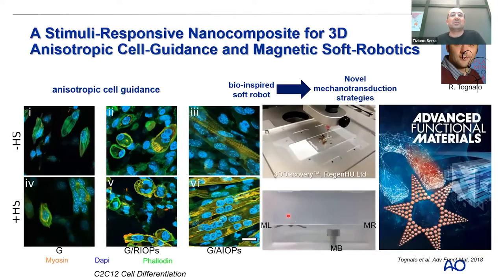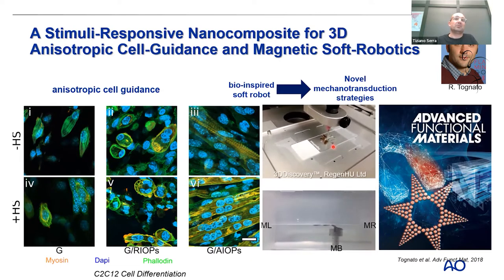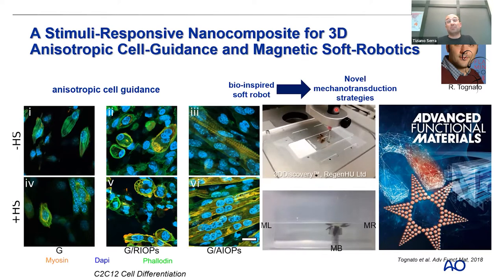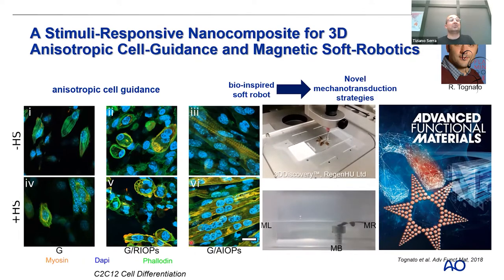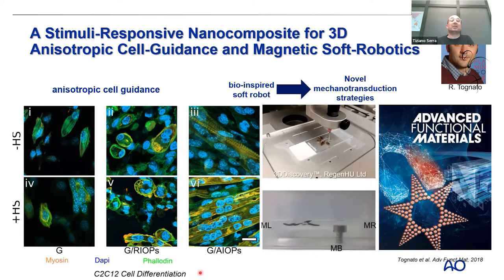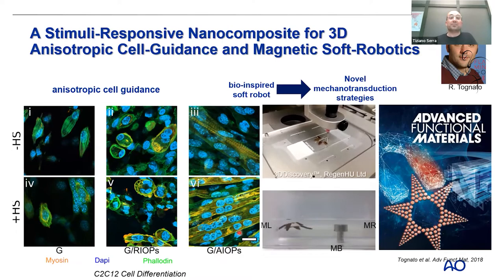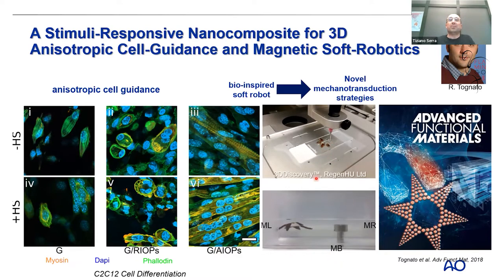We have recently studied the bioprinting of an ink that is a nanocomposite containing inorganic particles — in this case iron oxide particles — which give the bio-ink magnetic properties. We can use anisotropically aligned particles through a magnet to act as cell-instructive material. The cells present in this nanocomposite are able to align and fuse into each other; this is the case of skeletal muscle cells that fuse and create myotubes.